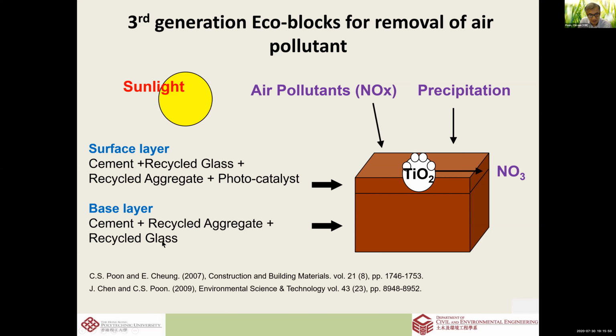Recycled aggregate, of course, has to meet certain criteria, and recycled glass has the concern of ASR, but we have addressed that, as I said. If you're interested, you can go to these publications. But on the surface layer, we put TiO2. The TiO2 is a nanoparticle material, and it has the ability to convert NO, not remove, but convert NO to NO3, and NO3 can be washed away.